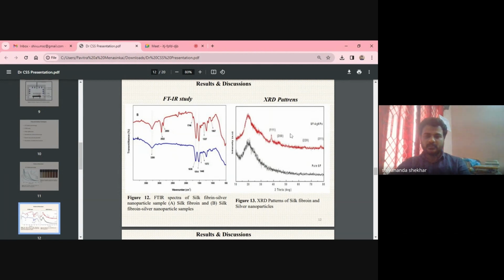And in the XRD patterns, for the pure silk fibroin, the diffraction pattern is observed around 20 degrees. This is due to the amino acid residues present on the silk fibroin surface. In the red color diffraction pattern, there are additional peaks at the 111, 200, 220, and 311 planes, corresponding to the 38, 44, 56, and 78 degree diffraction peaks. This confirms the formation of silver nanoparticles with a face-centered cubic structure. We also compared this data with the standard JCPDS files, and it exactly matches. This is the confirmation by XRD patterns.